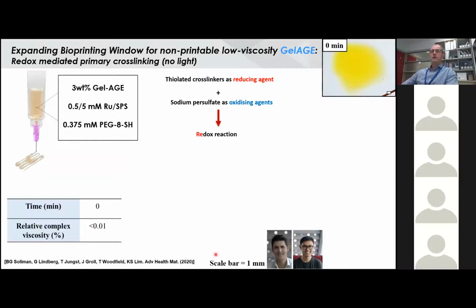So what are some other tricks and tips that we've published more recently? Again, this is led by Koen Lim and Bram Solomon in the group. What if we wanted to push the boundaries even further, and go to really low weight percent polymer concentration? In this case, if you take a 3% gel, for example, it's essentially extremely low viscosity, and you can't print with it. And it would be the same if you're taking very low concentration GelMA and other things.